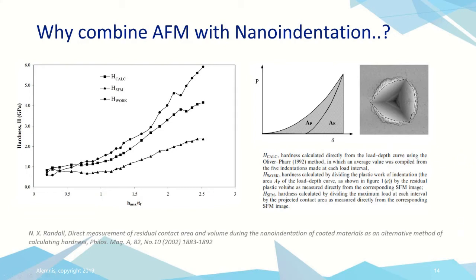Now, one of them, H-work here, this is the hardness calculated by dividing the plastic work of indentation, so the area AP here under the curve, by the residual plastic volume. Now, we get the residual plastic volume from defining the edges of our indent in the AFM image, and then by software, we can calculate the actual volume of this indent. And by dividing AP by the volume gives us H work, which we can see plotted here for those depths through the coating into the substrate.